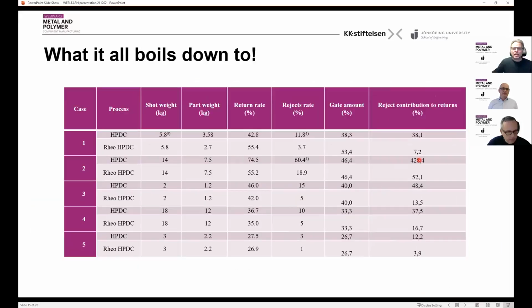But the essence here is still, if you look at the industry, we all know that rejection rates boil down to the bottom line of your economy. So it goes directly down to rejections, but nobody really cares about the return rate. Of course, it's important not to have a high return rate, but when it comes to the contribution from rejections or gating systems, the rejections in a foundry are essentially a minority when you have an efficient process. So if you look at the competitiveness of a company, rejects are of course important, but when it comes to the carbon footprint, gating systems are critical. And this is something that has not been properly addressed yet.